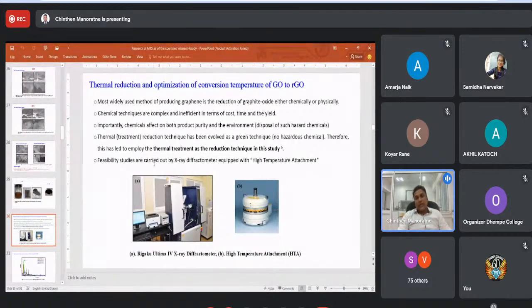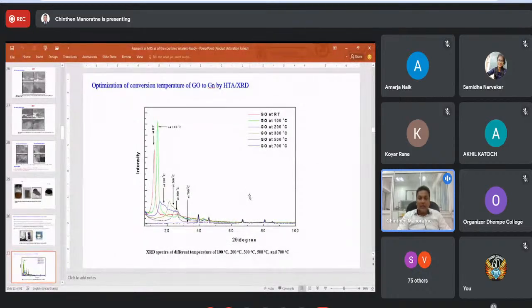To analyze the exact conversion temperature of graphite oxide to graphene, we use the high temperature attachment available with our XRD machine. Here you can see that we scanned our graphite oxide from room temperature to 700 degrees at different temperature intervals, and you can see the gradual conversion of graphite oxide to graphene, and at about 500 you can see the corresponding peak for graphene, and above that the structure collapses and carbonizes.